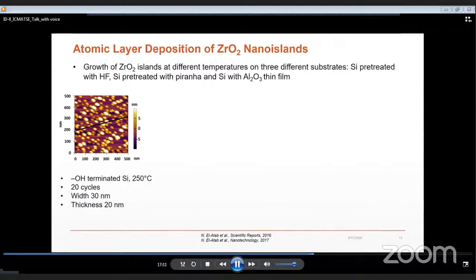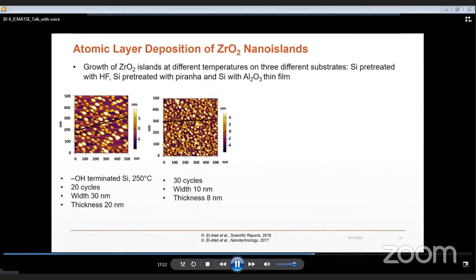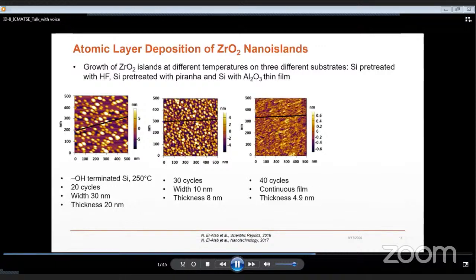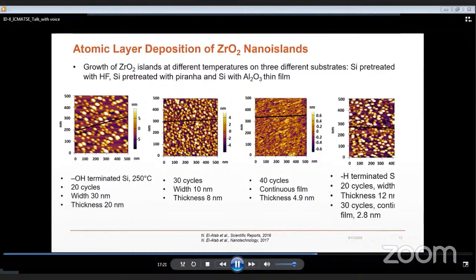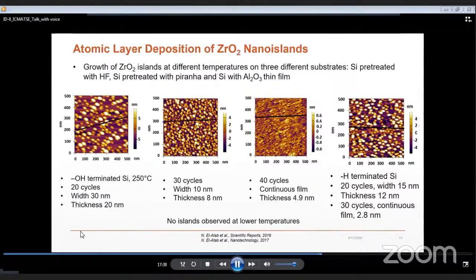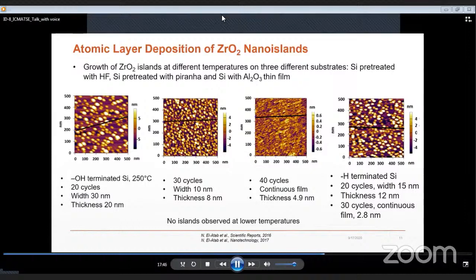Then as the number of cycles is increased to 30, the density of islands is increased, but their size is reduced, until a continuous film with a thinner thickness is obtained with 40 ALD cycles. On the HF-etched sample, which is H-terminated, the number of islands obtained after 20 ALD cycles is higher than in the case of the hydroxyl-terminated sample. With 30 ALD cycles, a continuous thin film with 2.8 nanometer thickness is obtained. The reason is that the H termination acts as a surfactant that reduces the mobility of the atoms and thus results in a higher density of smaller islands.